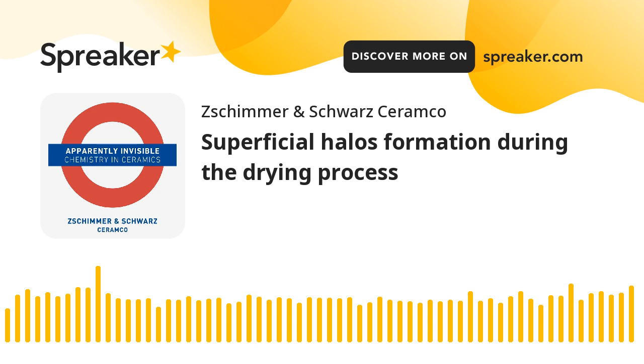This different evaporation process that takes place in the lower and upper parts of the tile, in some rare cases, produces longitudinal bands or stripes that may remain visible even after the drying cycle. Basically, there are more or less brilliant halos that, in extreme cases, and this must be underlined, in extreme cases, despite the following application of inks and glazes, may persist and be visible even after firing. The problem appears especially with technical ceramics production or in case of non-massive application along the glazing line. And so, from a chemical point of view, what is the origin of this uneven brilliance of the surface?